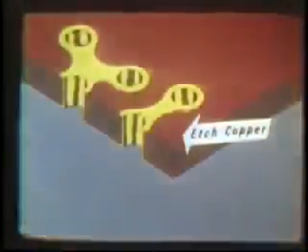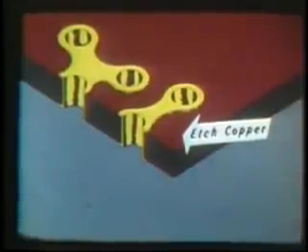The etchant containing ferric chloride will dissolve copper, but it has no effect on gold. So the gold protects the underlayer of copper from the etching solutions. Metals other than gold might be used if they would resist the etch, protect the copper, and be readily soldered. We now have a flat of several circuit boards with gold-plated copper conductors. This plating extends through the holes, which will receive component leads. A scrubbing completely cleans the flats of any chemicals or residue left from the plating process.